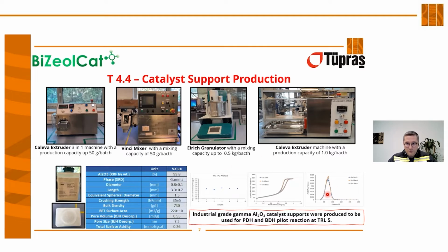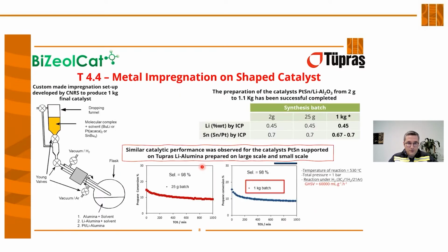You can see in the graph, this data was taken from different batches. This is the NH3 TPD analysis. We obtained the same total acid site, and we have also the same BET nitrogen absorption and desorption graph, and the same pore size with different sizes. So our production is very robust in terms of material properties.